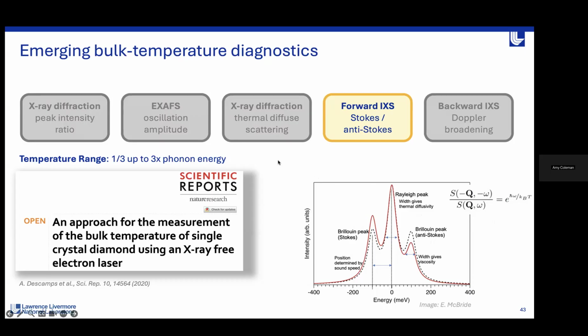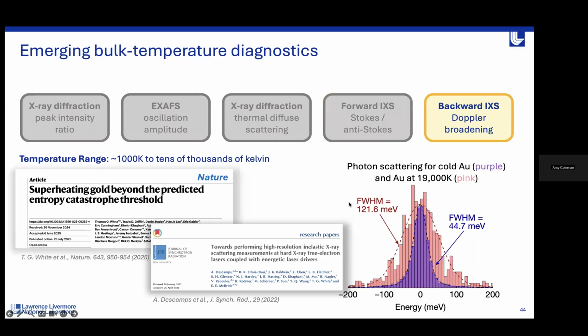One of the downsides of this is it's only viable in a temperature range where your temperature is comparable to the phonon energy, so we're talking about a third of phonon energy up to 3 times phonon energy. You're slightly limited in the range you can explore, but it's nice that it doesn't rely on a model the same way the first three techniques do.